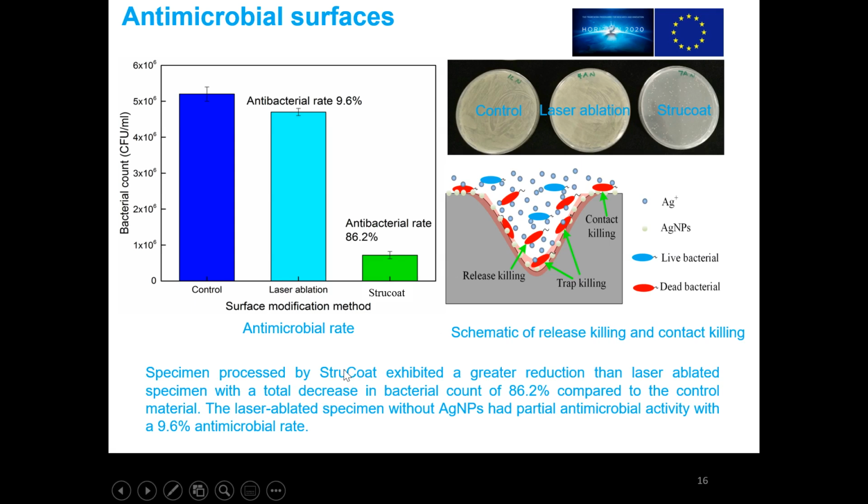Then we did the antimicrobial test and found that the StruCoat surface has an antibacterial rate of 86.2%. So the microstructure can help the adhesion of the silver nanoparticles. It will release silver ions and kill the bacteria.